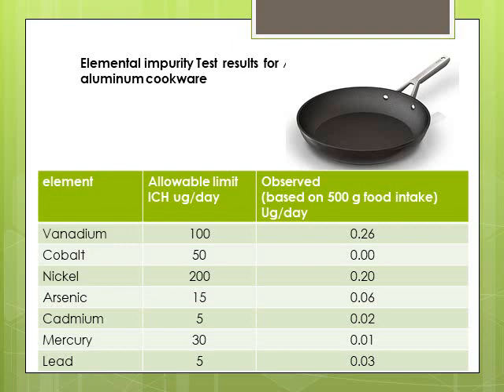500 grams or half a kilo of food prepared in this pot, so put it this way. So if you make a food mostly boiling water, sort of like a stew, and you eat 500 grams, half a kilo, you would be exposed to 0.26 microgram vanadium. Cobalt, you will expose nothing. Nickel, you will get 0.2 microgram. Arsenic, 0.06. Cadmium, 0.02. Mercury, 0.01. Lead, 0.03. All these numbers are significantly less than the allowable limit.